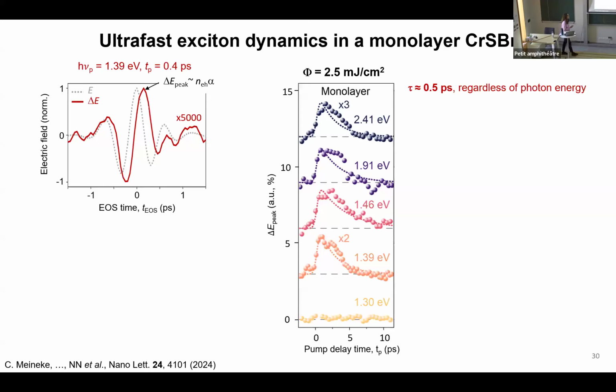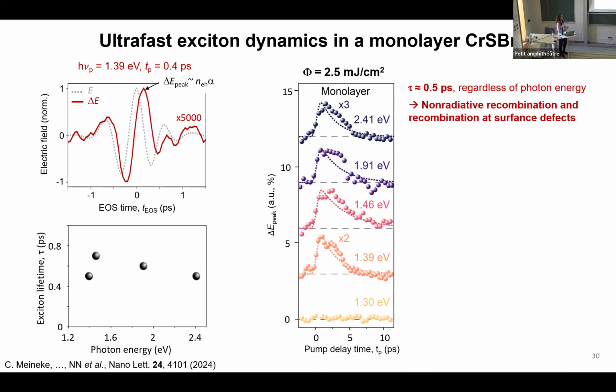It is only 0.5 picoseconds. Remember that the recombination dynamics in the bulk was 10 to hundreds of picoseconds. So it is an order of magnitude smaller than what we saw in the bulk. How can we understand this? There are a few ways to verify what is the source of this ultra-fast recombination. First off, if we follow the relaxation dynamics as a function of the photon energy, we see that it remains more or less constant. It does not depend on the photon energy.